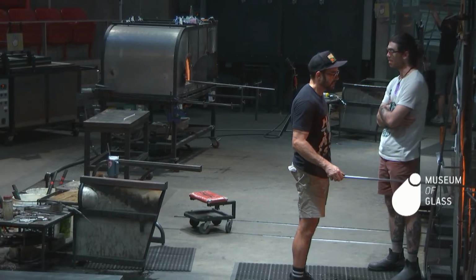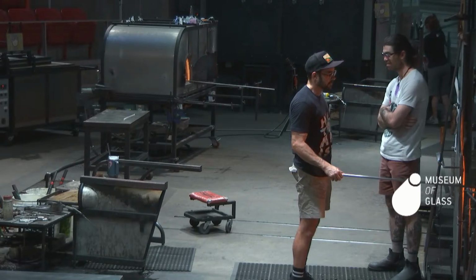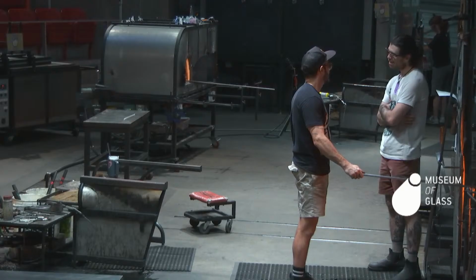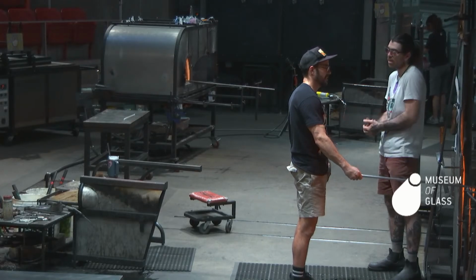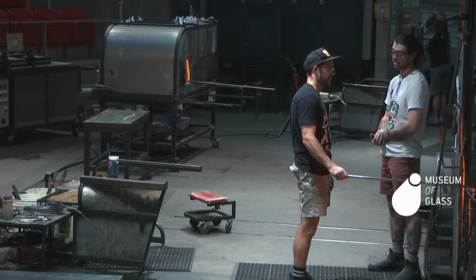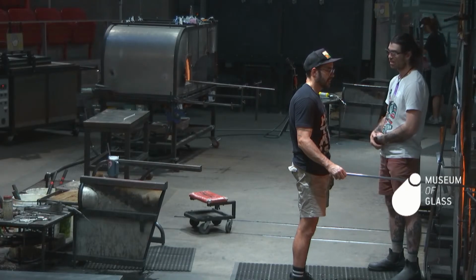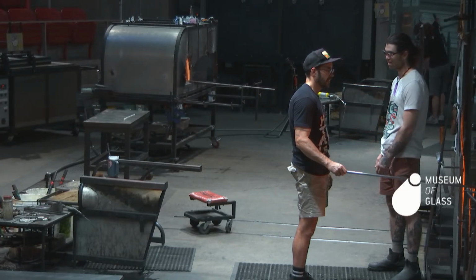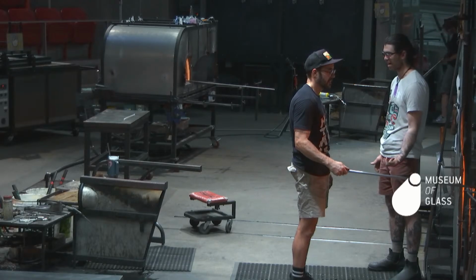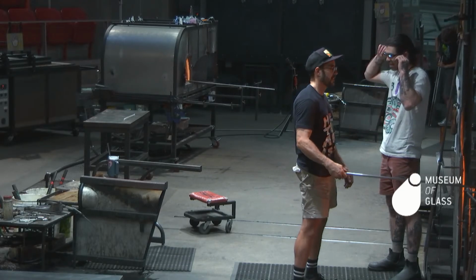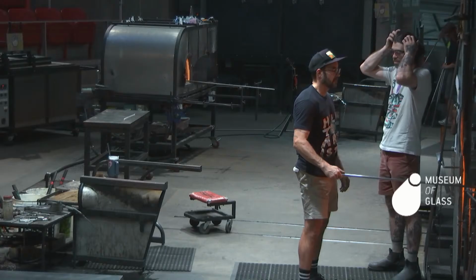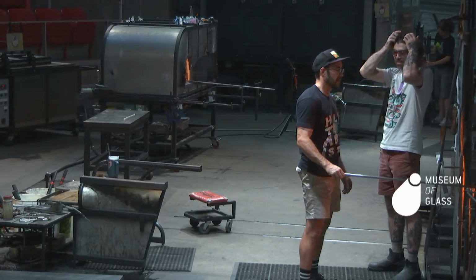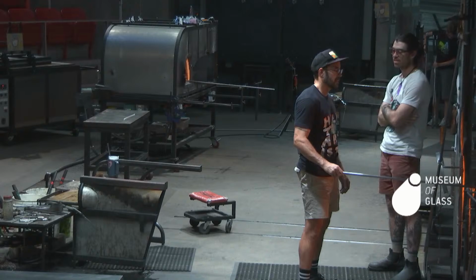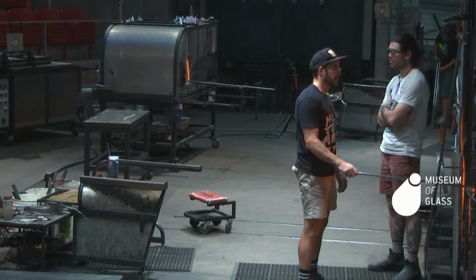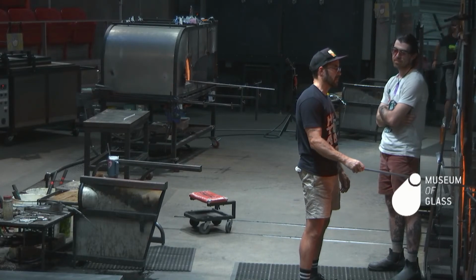So that's why we had to do the Swedish overlay. Glass blowing's a layering process, and most of the time when you use color, you put the color over a clear bubble, and then you encase it in more clear. But they want the color to be on the outside, so we can't encase this in more clear. So that blue glass is the outermost layer, and then there's white right underneath it. They can carve into it or sandblast it to remove some of the blue to show the white underneath. And that's why they need that to be on the outside layer.